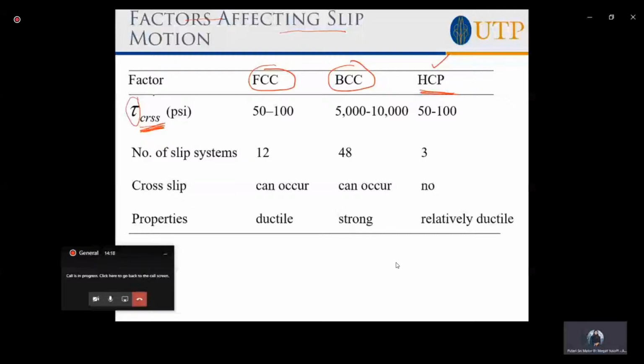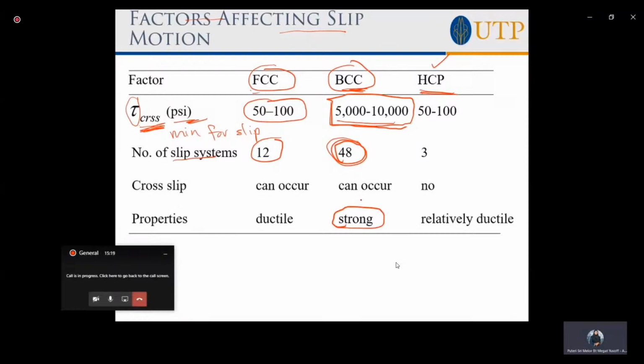Now, number of slip systems in FCC is only 12, but BCC has lots, right? But it does not matter because even though you have more here, 48, if the shear stress required to slip is too high, then the property becomes strong because it's difficult to move your dislocation. You cannot cause slip to happen easily. You need to reach this value before it can slip. Therefore, your material becomes stronger than FCC.